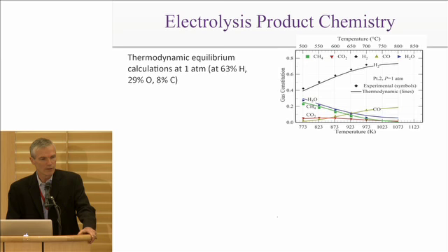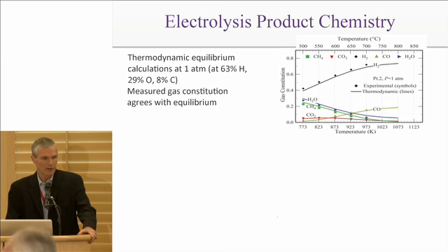So nothing special, and that doesn't do us any good, but it turns out that if you actually drop the operating temperature, say to 600 degrees centigrade or so, you actually start getting some different products. In particular, you can see you're starting to produce a substantial amount of methane in the product mix. Okay? And by the way, I just want to illustrate these data points show that these are actually measured compositions, so showing that the thermodynamic compositions are actually reached in practice in these kinds of devices.